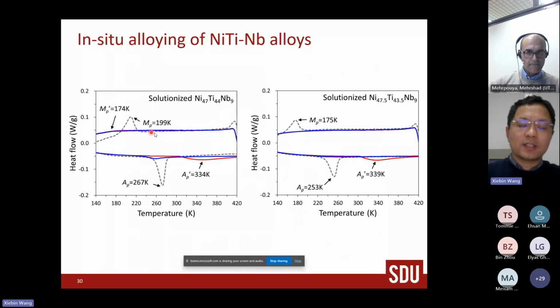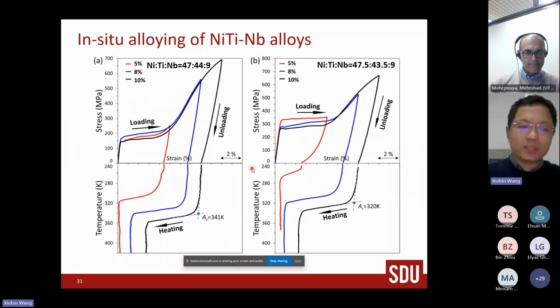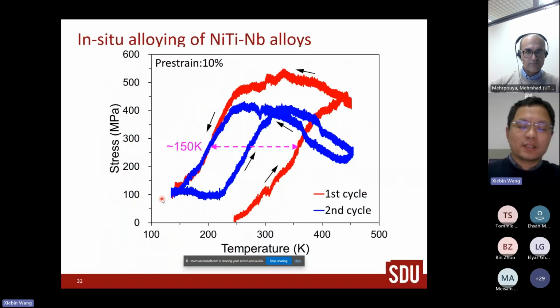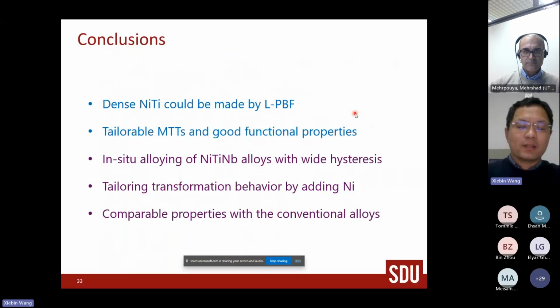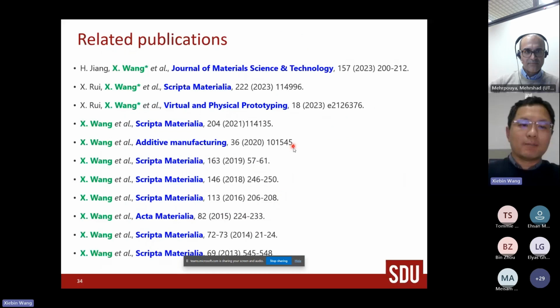And then we checked the transformation hysteresis, which is so large and comparable to the conventional alloys. And we checked the shape memory effect. So good shape memory effect and could be used for couplings. And also we checked the recovery stress with a change of temperature, and it also shows very good results. And these are the conclusions, and this is related to publications.